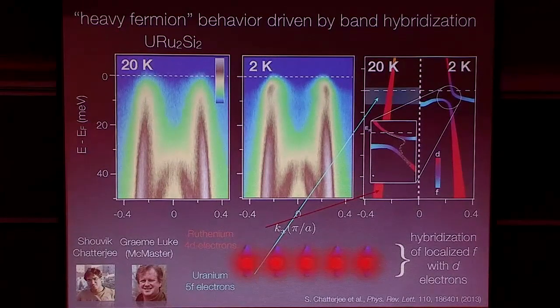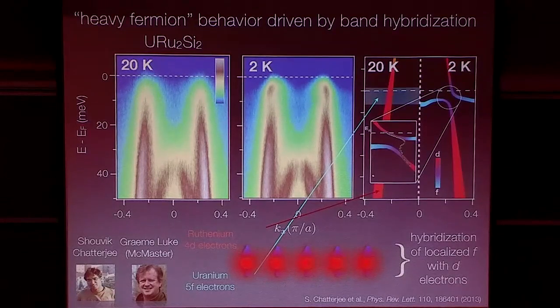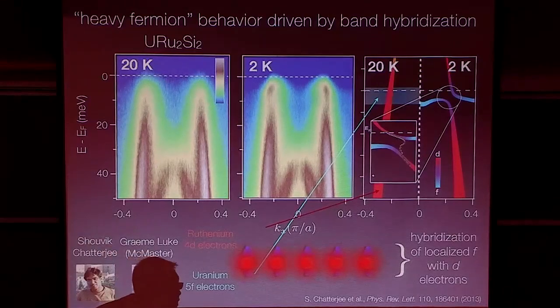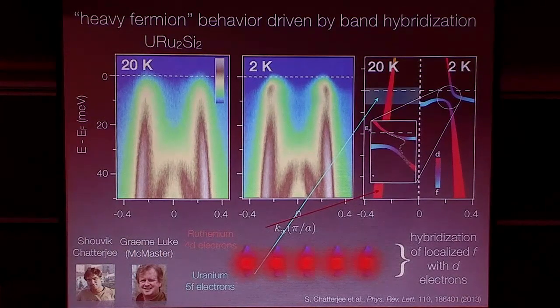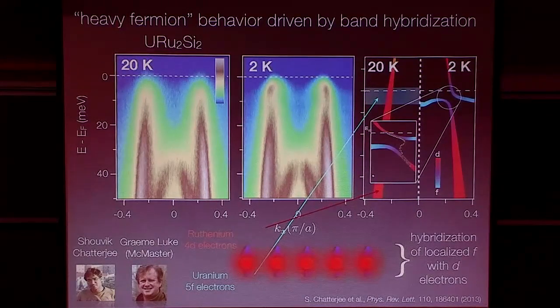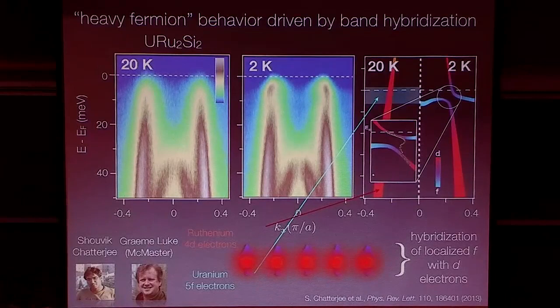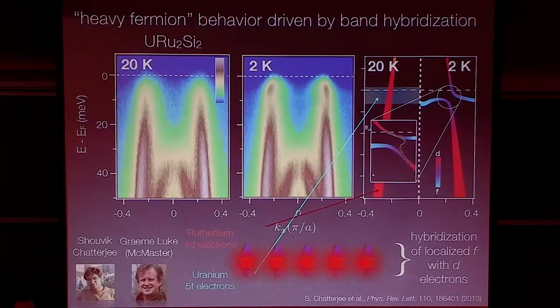It turns out there's a lot of crystal field splitting of the F states, so some actually sit very close to the Fermi level, and at different photon energies you can see them very distinctly. The crystal field electron orbital structure of these 4F states is pretty nontrivial. In terms of how far above the Fermi level you can look: basically it's limited by instrumental resolution and Fermi-Dirac broadening. If you want to look a little bit above the Fermi level, you can heat your sample up and thermally populate states, though that also increases the scattering rate. We'll heat it to 100 Kelvin and try to look at states near the Fermi level, but that's basically kT — so only a few to 10 millielectron volts.